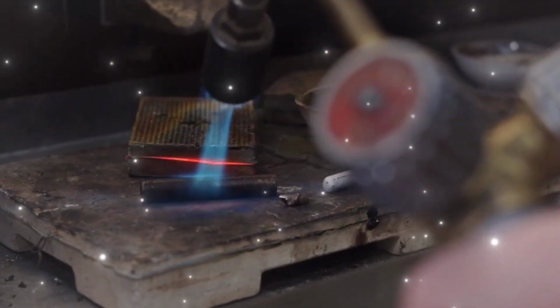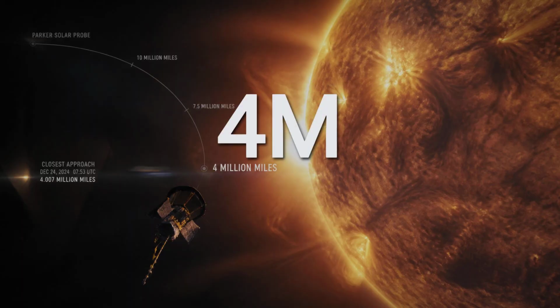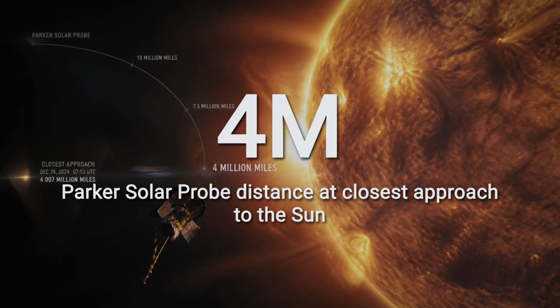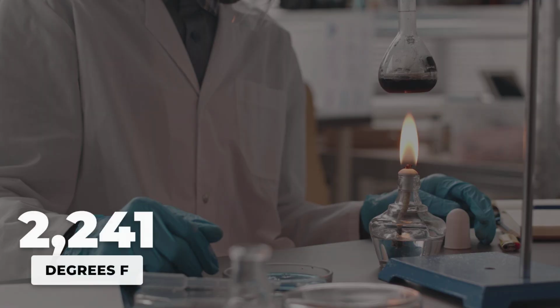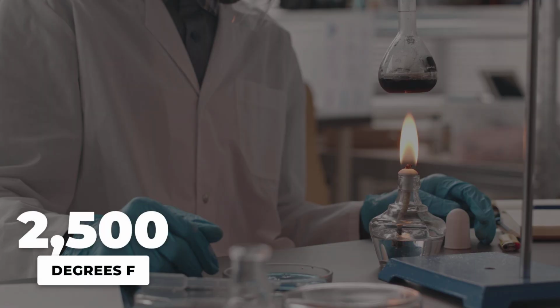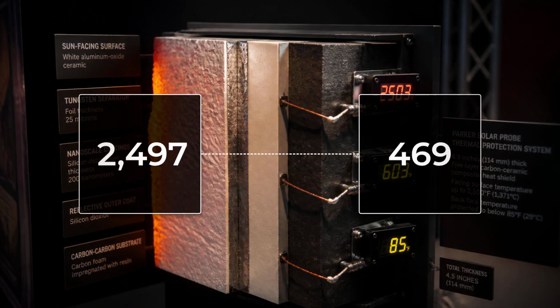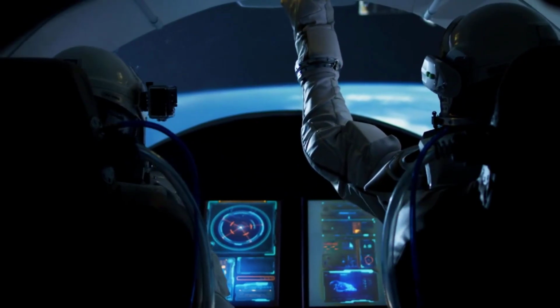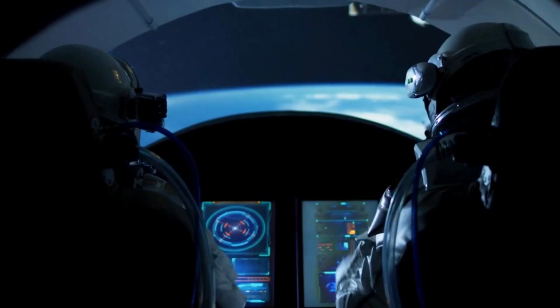This multi-layered optical system delivers an extraordinary thermal performance. At the spacecraft's closest approach, roughly 4 million miles from the sun, the front face of the shield reaches a blistering 2,500 degrees Fahrenheit. But just 4.5 inches behind it, the rear face registers only 600 degrees, while the scientific instruments operate at a comfortable 85 degrees. It is a temperature drop of nearly 2,400 degrees, achieved across a barrier thinner than a standard household brick.